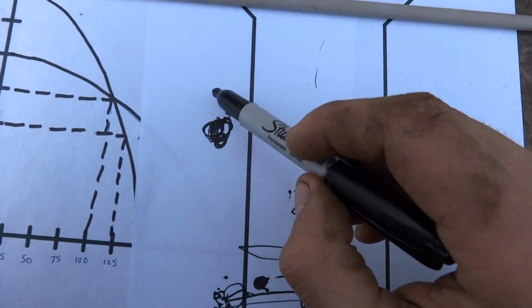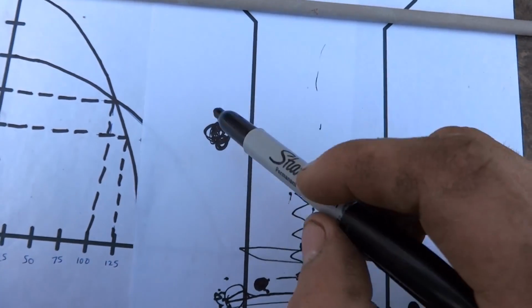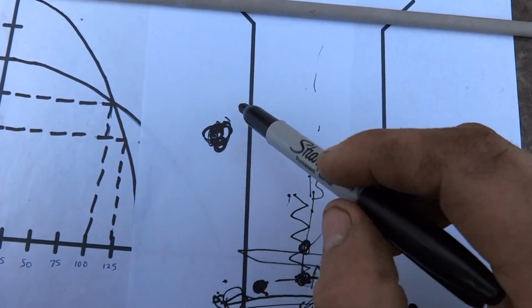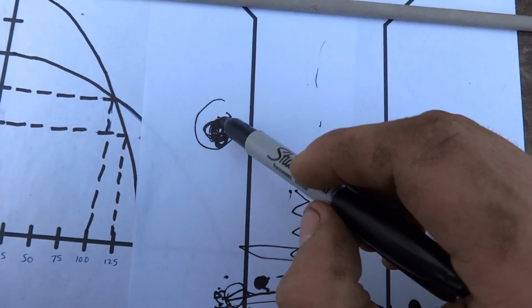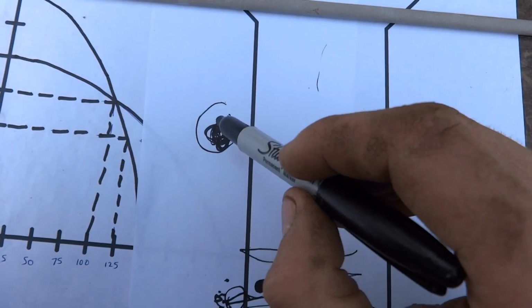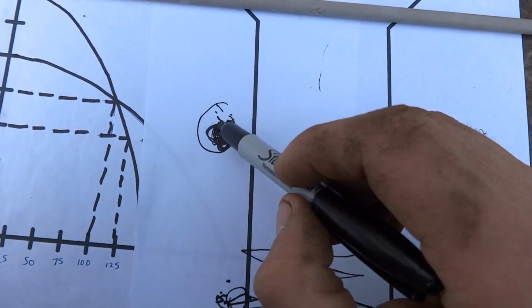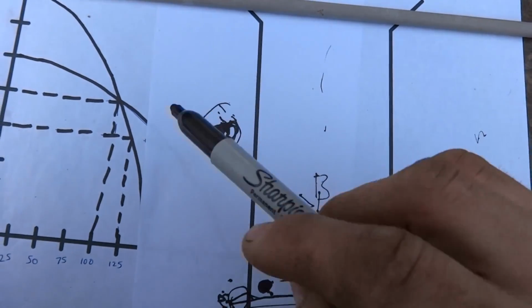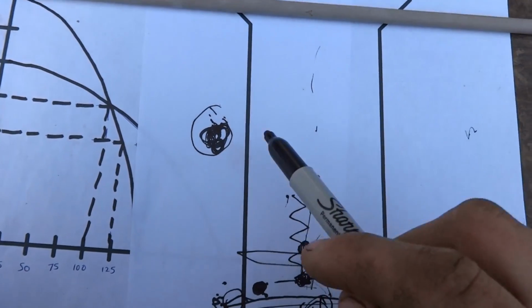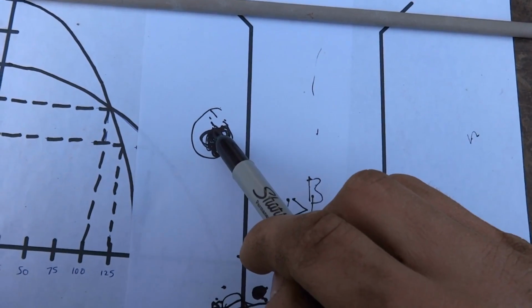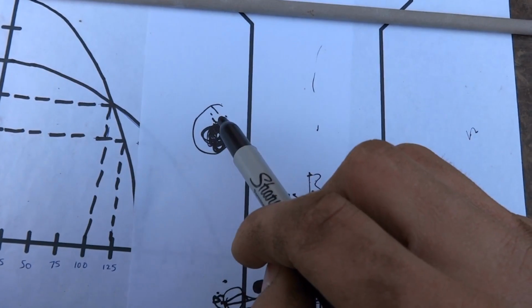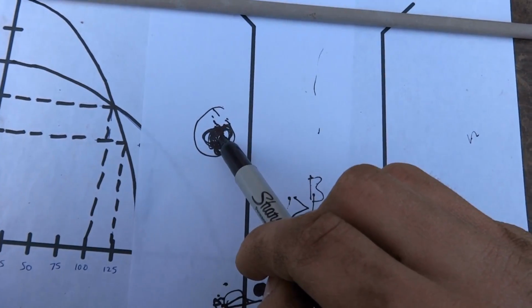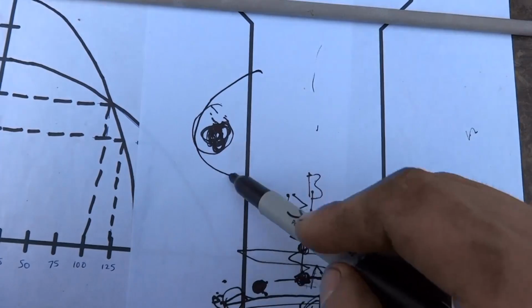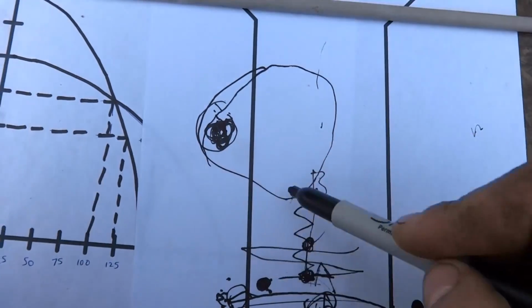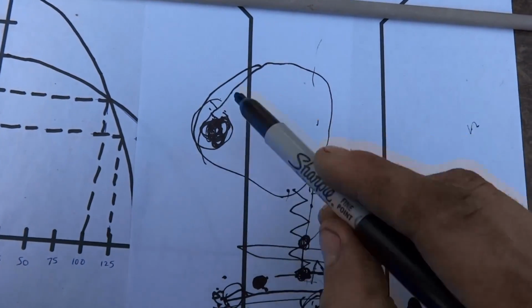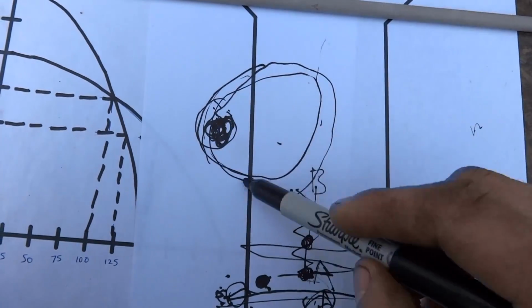With the tight arc, amperage increases, burn-off rate increases, voltage drops off, so he's able to pour a lot of metal in a very short amount of time. He's able to dump metal into the side bevel here, and because the voltage decreases, the puddle solidifies. He moves from the left-hand side. He's content and happy with the amount of fill he deposited into left-hand side bevel, and this is pretty much how much metal he's going to deposit holding a tight arc. He's going to deposit a ton of metal in there.